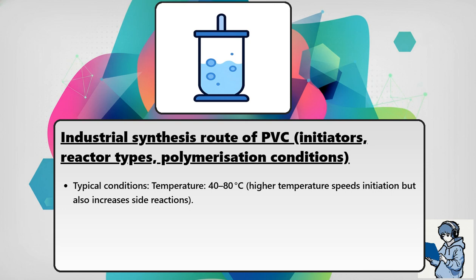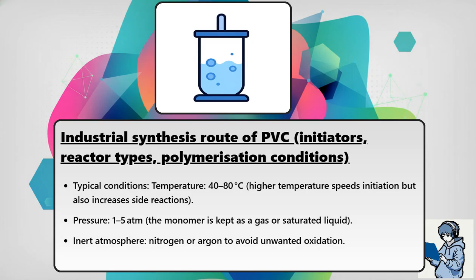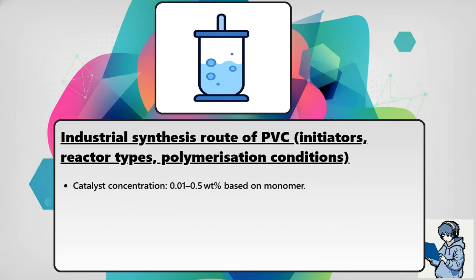Typical conditions. Temperature, 40 to 80 degrees Celsius. Higher temperature speeds initiation but also increases side reactions. Pressure, 1 to 5 atmospheres. The monomer is kept as a gas or saturated liquid. Inert atmosphere, nitrogen or argon, to avoid unwanted oxidation. Reaction time, 1 to 3 hours for batch, continuous for loop reactors. Catalyst concentration, 0.01 to 0.5 weight percent based on monomer.